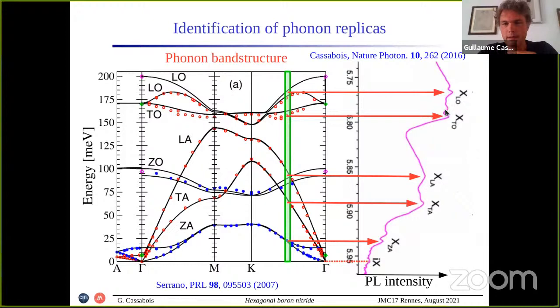Here I am plotting the rotated PL spectrum of HBN compared to the different phonon branches, and it perfectly aligns with the PL spectrum. Basically, this dim emission corresponds to the indirect bandgap, and then we have emission assisted by this phonon branch, this second one here, the third one here, etc. So we have a series of phonon-assisted lines. At high energy are the lines assisted by emission of acoustic phonons, and at lower energy, the lines assisted by optical phonons.